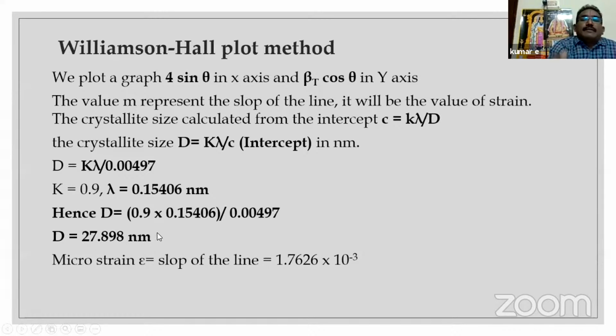This method is an accurate one. In the previous method, we calculated the crystallite size using the Debye-Scherrer formula. It is an approximate one, but the WH method is accurate. The values are very similar. In the Debye-Scherrer formula, we got the crystallite size as 26 nanometer. Here, it is 27.89 nanometer. Then the microstrain, or the slope of the line, is equal to 1.7626 into 10 to the power minus 3.